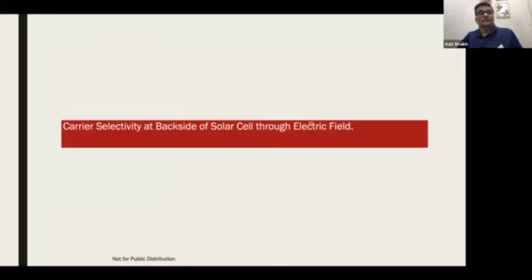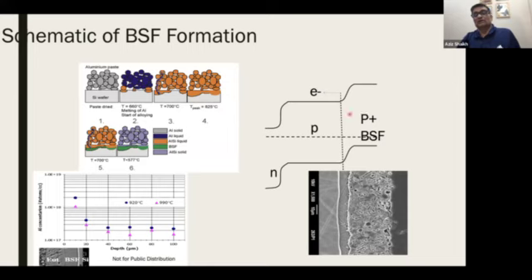So the line widths are continuing to shrink. Now your question, the carrier selectivity at the backside of the solar cell through electric field. So this is what goes on. In the traditional solar cell, we used to form a back surface field by putting aluminum. What you see here is a cross section. This is aluminum, this is the silicon wafer, and here is the back surface field. This back surface field creates a barrier for the carriers. So this is a P plus layer. There is a bending of the band diagram, and it is applicable for both mono wafers as well as multi wafers. They both use this technique. So whether you buy a mono wafer module, it would have an aluminum backside. If you buy multi, it would also have an aluminum backside.